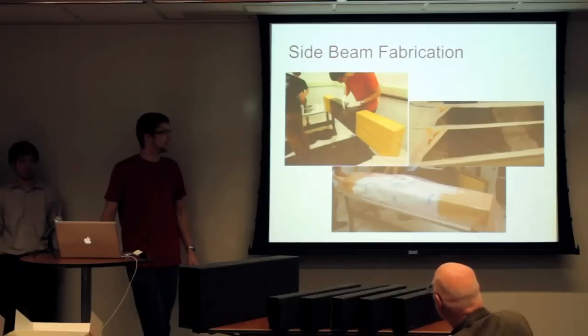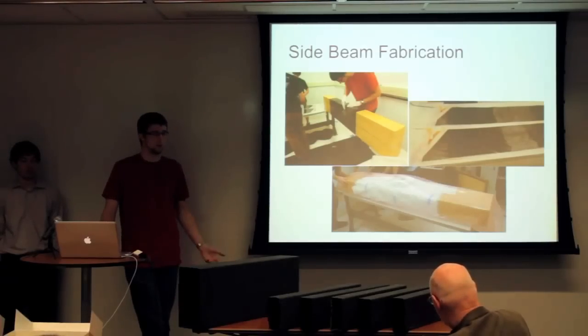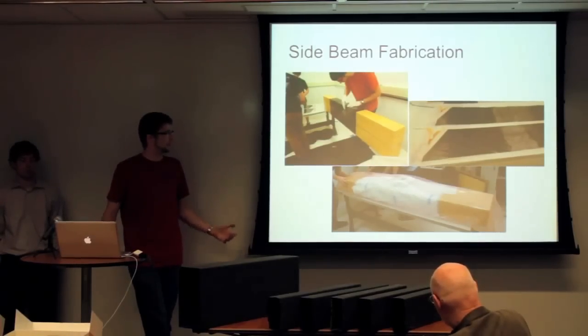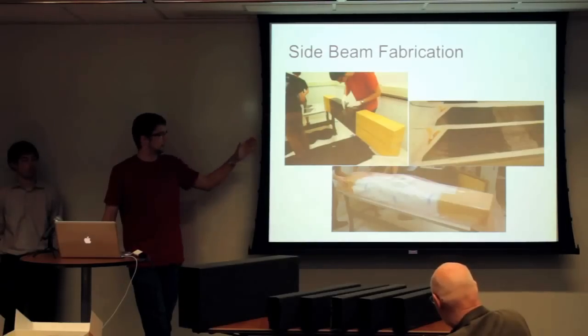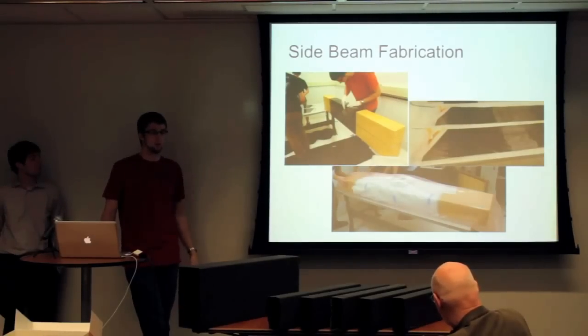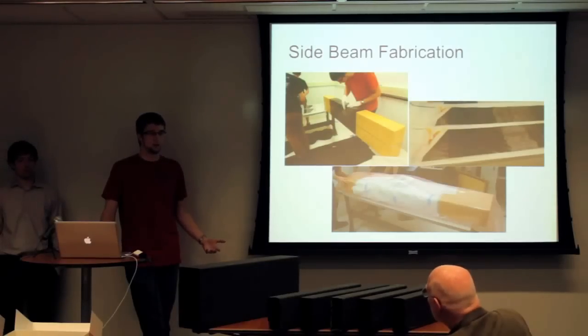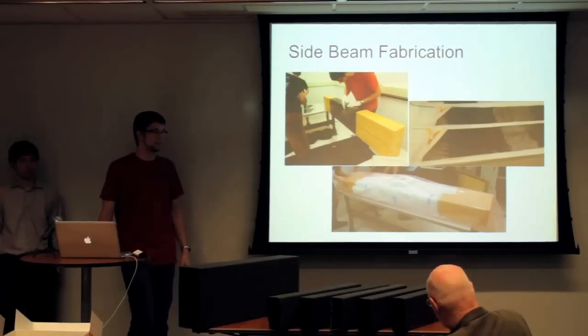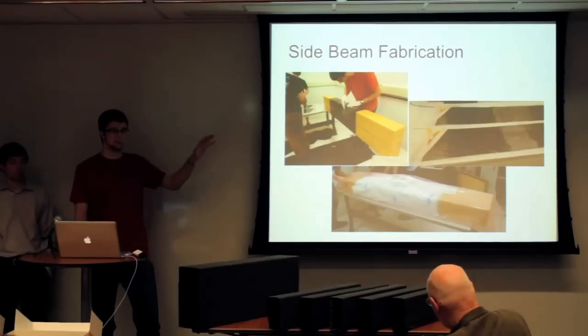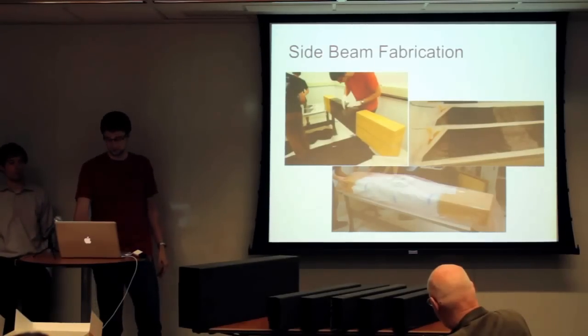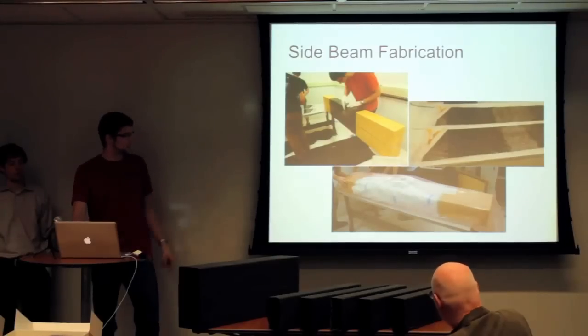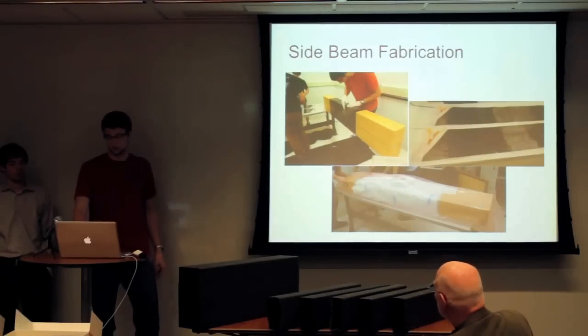But it gets increasingly hard to line them up right, because the important part isn't so much that they meet at the ends perfectly. It's more important that we actually have the right angles, because that's what's going to be taking the load later on, since carbon fiber is only strong along the fiber. So we had to make sure we actually get the angles right, and with the larger parts it gets really hard because gravity pulls these things down and slowly starts sagging on all sides, and it was difficult. But we finally succeeded. We wrapped it, and that's the result for that.